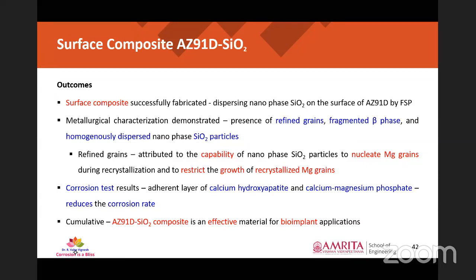The refinement of grains is attributed to the capability of nanophase silica particles to nucleate magnesium grains during the recrystallization phenomenon and to restrict the growth of recrystallized magnesium grains. The corrosion test results indicate the formation of an adherent layer of calcium hydroxyapatite and calcium magnesium phosphate layer that reduces the corrosion rate of the material. Cumulatively speaking, we could say that this composite is an effective material for bioimplant applications.